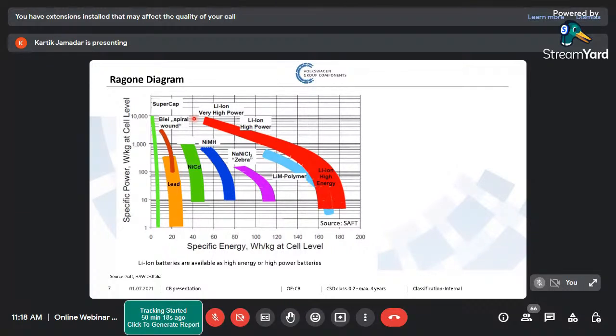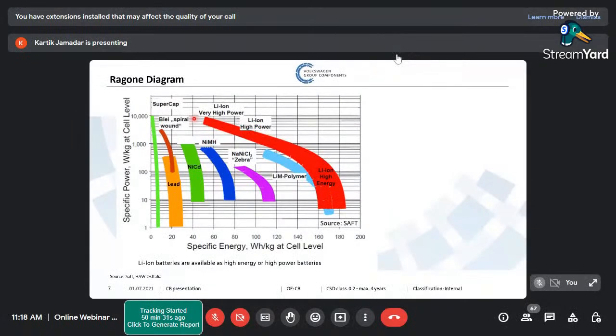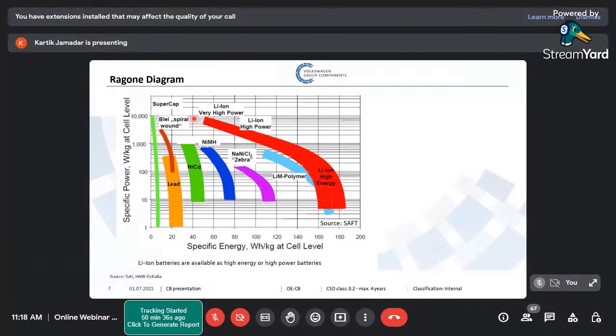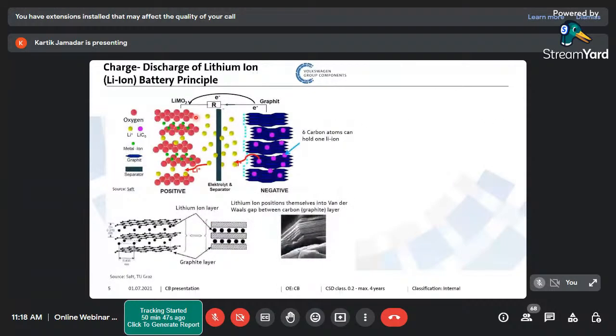It means if I want high power, meaning a high current in a short period of time, lithium ion can give you that. If you need high energy, that also it can give you. The only thing is, it cannot give both simultaneously. The principle is very similar, but either it can give high energy or high power, not both at the same time. The reason, I can explain here. The lithium ion has to move from the graphite to the cathode. This is a distance which they have to move.